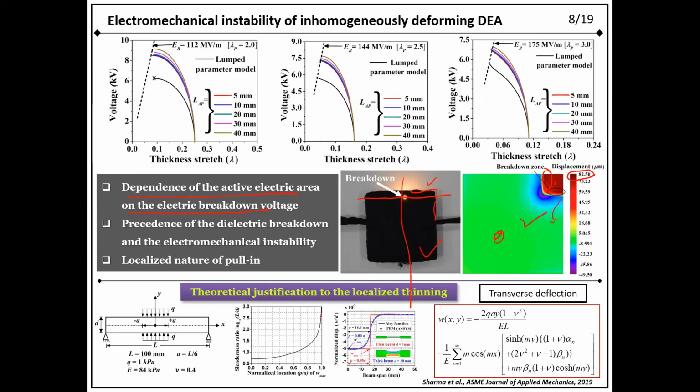In the finite element model we also observe that the deformation levels are maximum near this interface, and that correlates with the higher deformation. This will be the point where a short circuit will happen first, the thinning area, where the membrane thickness will be less.